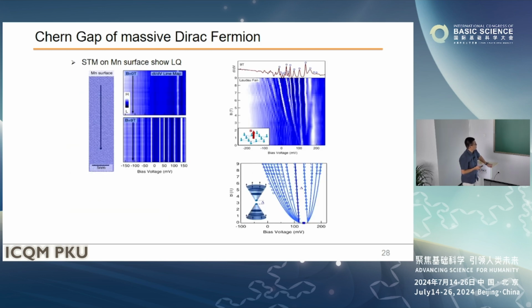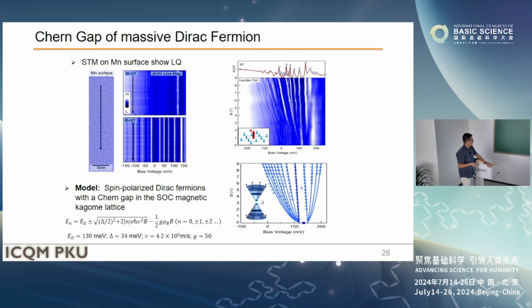All right. So our collaborators did some STM measurements on the manganese layer. The most important observation is that he scanned the field and the gate voltage or something. Then he observed an interesting Landau fan diagram for a massive Dirac fermion, meaning this Dirac fermion has a small gap around 50 meV, but this gap is topologically nontrivial. We can use a spin-polarized Dirac fermion with a Chern gap in the kagome magnet, using this model to reproduce this shape of the Landau fan diagram, and to obtain some parameters. The delta is 34 meV, sorry, not 50.